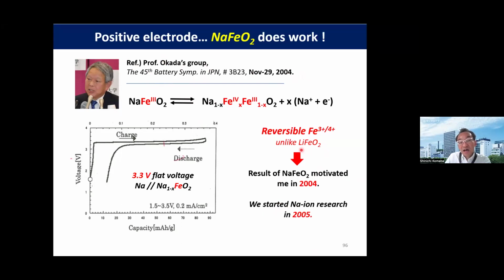But in lithium iron oxide, the iron 3+/4+ redox reaction is completely inactive, or very difficult to oxidize into 4+ iron. But by replacing lithium with sodium, such an electrochemical reaction is highly reactive with only one plateau, not multiple potential reactions. And the iron 3+/4+ redox couple is highly reversible, and the potential is 3.3 volts. I was very surprised during this oral talk.